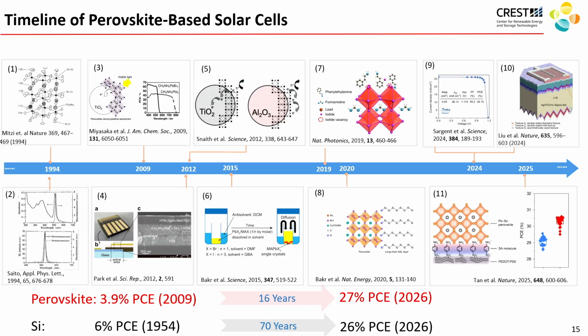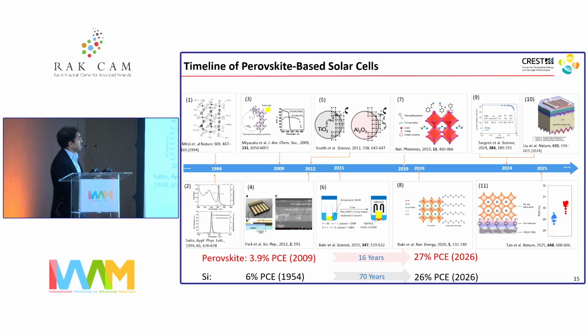Just to give you a bit of a historical perspective, the first significant applications of perovskites in devices happened when David Mitzi tried to apply two-dimensional perovskites in transistors, and then from that point things were quiet until in 2009, Miyasaka started using perovskites as substitutes for dyes in dye-sensitized solar cells. That first iteration of the solar cell only lived for a few seconds, I guess, and was very fragile. Eventually, Park and Gratzel replaced the liquid in the dye-sensitized solar cell with a solid-state hole transport layer.